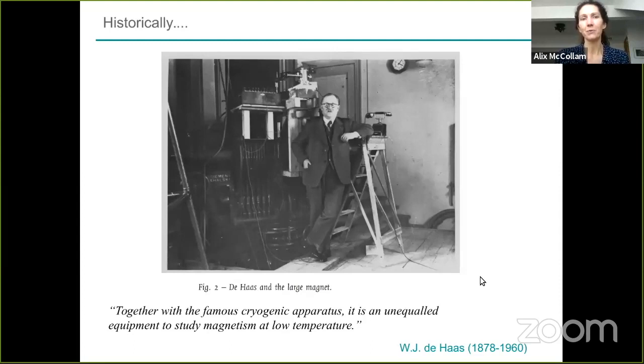And it's not totally straightforward to continue your zero field experiments in high magnetic field. So doing things like resistivity is relatively straightforward. The de Haas-van Alphen effect is a very nice measurement to do in high magnetic field because it becomes effectively exponentially more sensitive as you increase the magnetic field. Specific heat is still a very difficult measurement to do. It can be done in the DC fields rather well, so up to 35 or 45 Tesla. Doing heat capacity measurements in pulse field is more difficult.